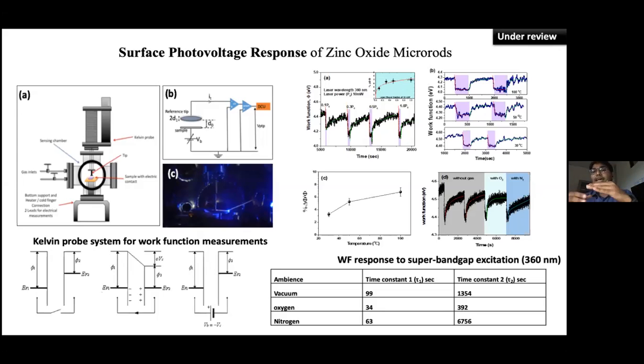It basically has a tip which oscillates over the sample surface, and the tip is made in such a way that it forms a parallel plate geometry like a capacitor. When the tip oscillates at a given frequency, the capacitance formed by these two parallel surfaces also oscillates. That sets up a back current in the system, and when you apply an opposing bias, you are nullifying that current, and that bias is the same as the difference between the Fermi levels of the two things, the tip and your sample. So it is called the contact potential difference.